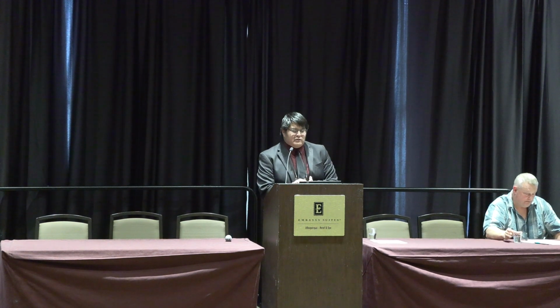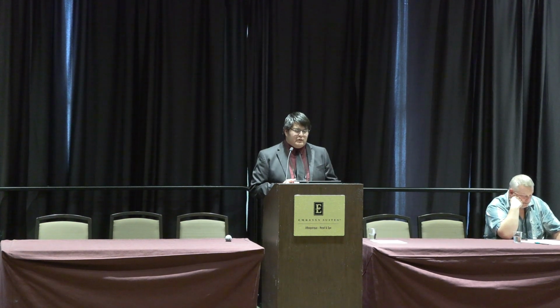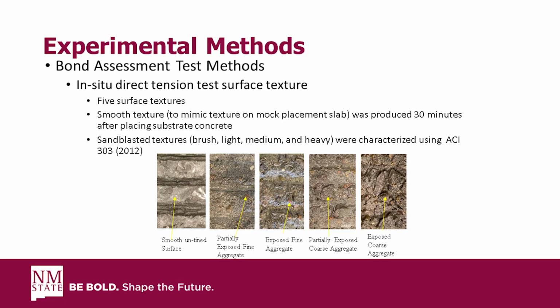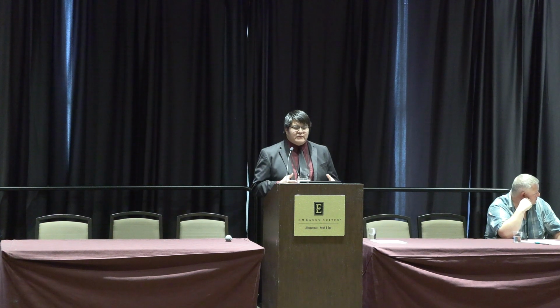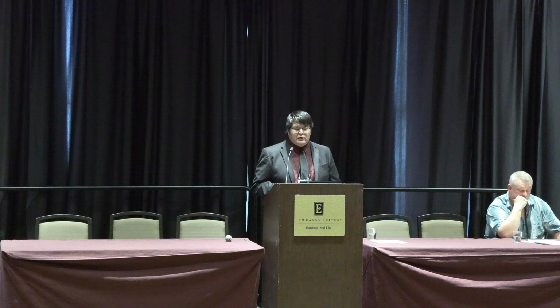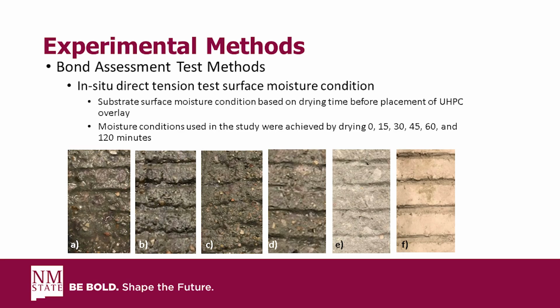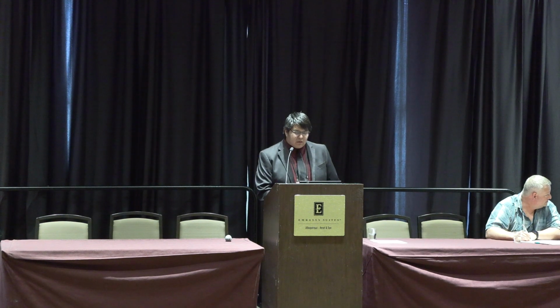Going from 0 minutes, of course, we're maintaining moisture, and then at 15 minutes we allow it to dry for 15 minutes, and then 30 minutes, and then 45 minutes would be what we define as saturated surface dry. This is the last case where there's visible moisture on that surface. And then we go into our dry cases where we allow it to dry for 1 hour or 60 minutes, that's figure E here. And then what we define as dry is drying for 2 hours, shown in figure F. Okay.